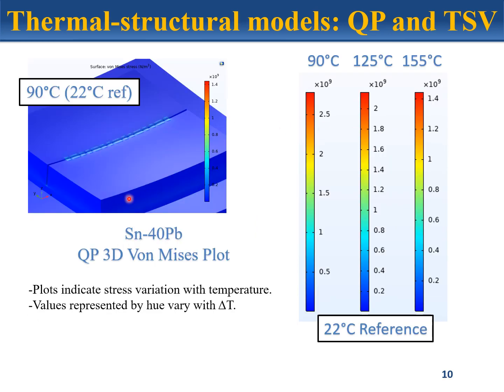Here we see a diagram representing the stress caused by the electrical currents flowing through the contacts, or nodules. This simulation was done with the nodule set to 90 degrees Celsius, with the ambient temperature set to 22 degrees Celsius. The figure shows a von Mises plot of the structural deformation of the structure. And here on the right side, we can see the different stress distribution based on different operating temperatures of the traces. All of these were set at 22 degrees Celsius ambient temperature.